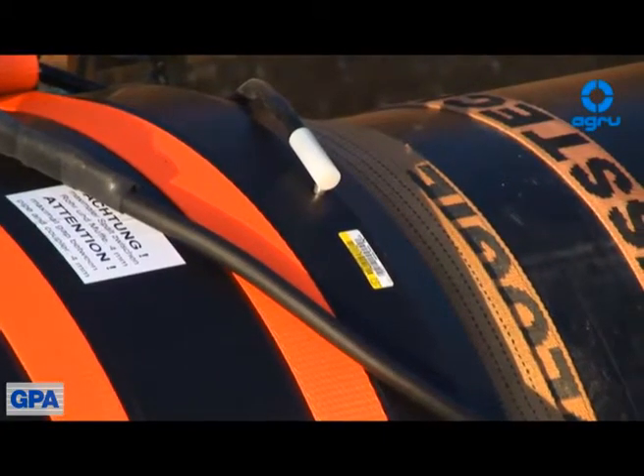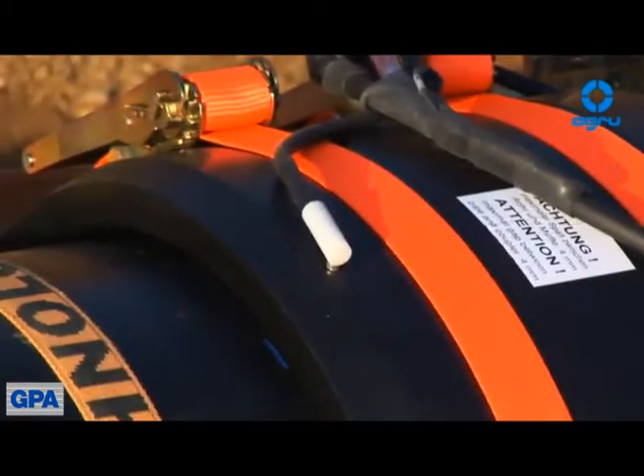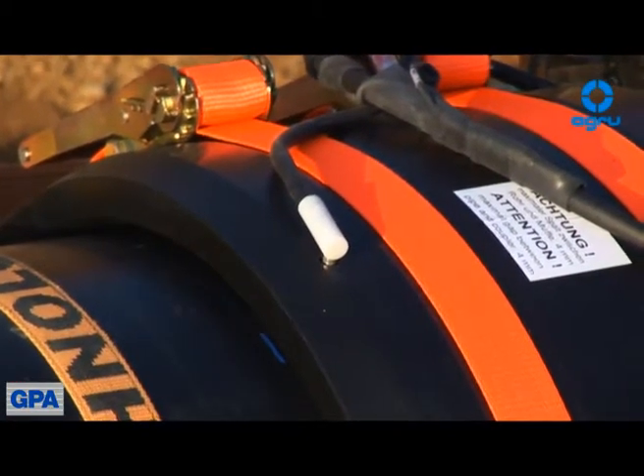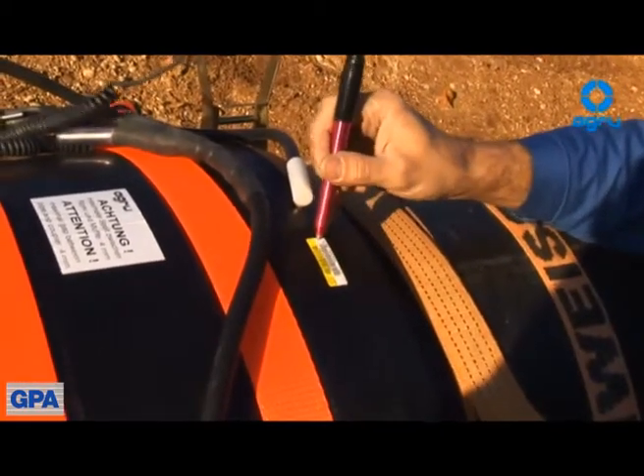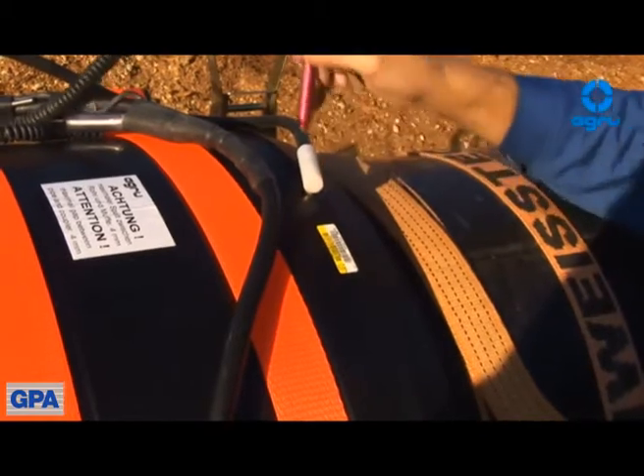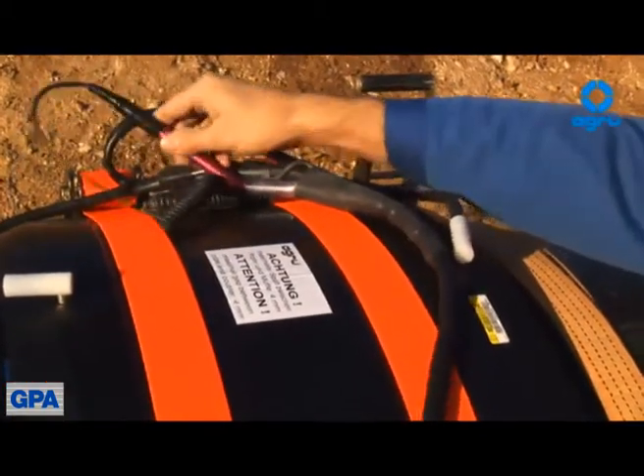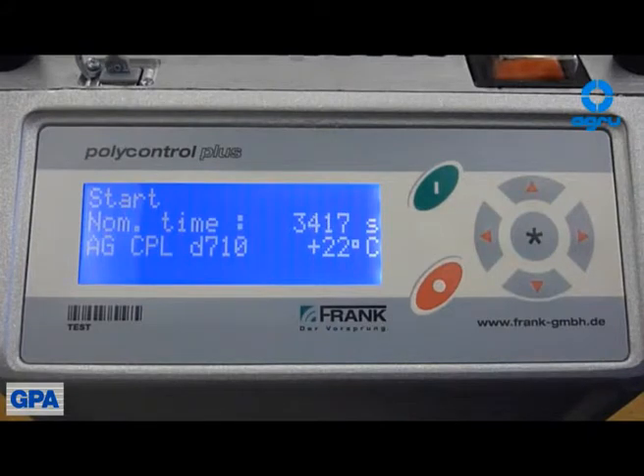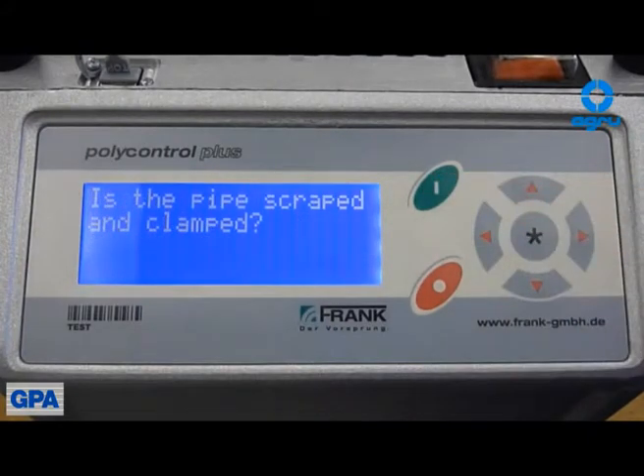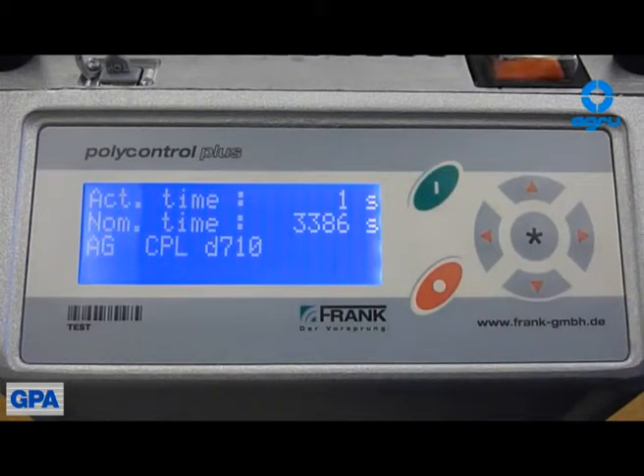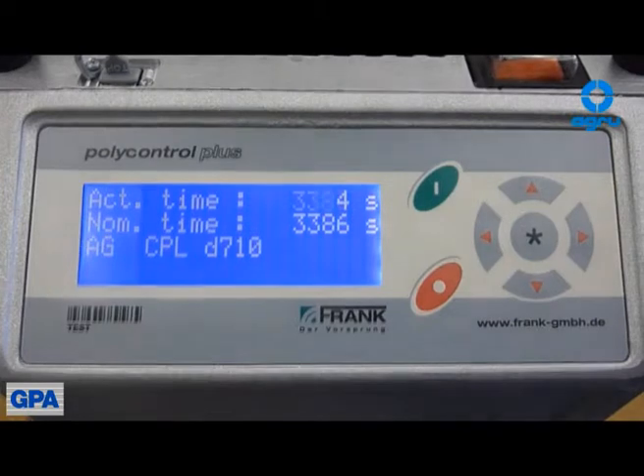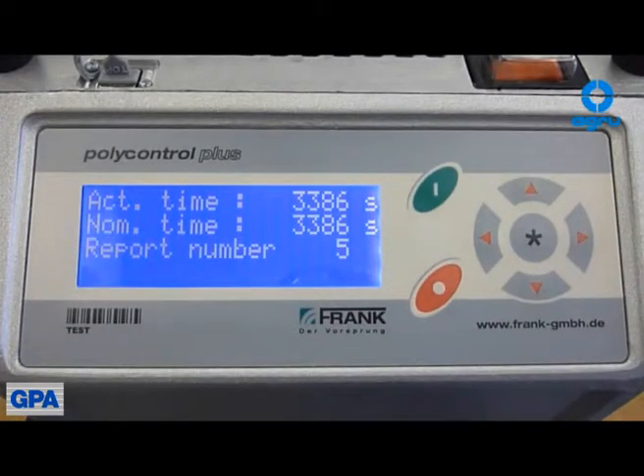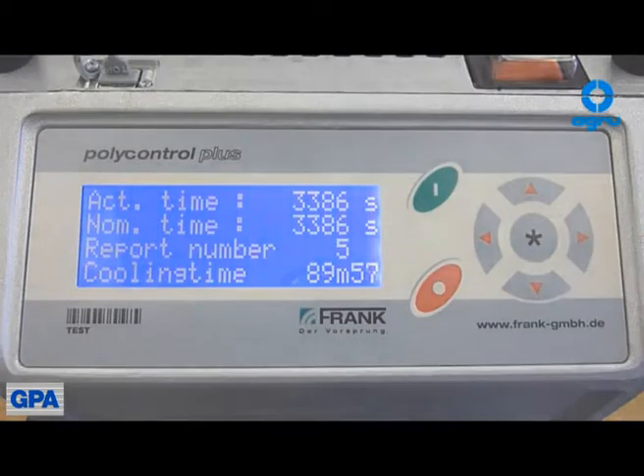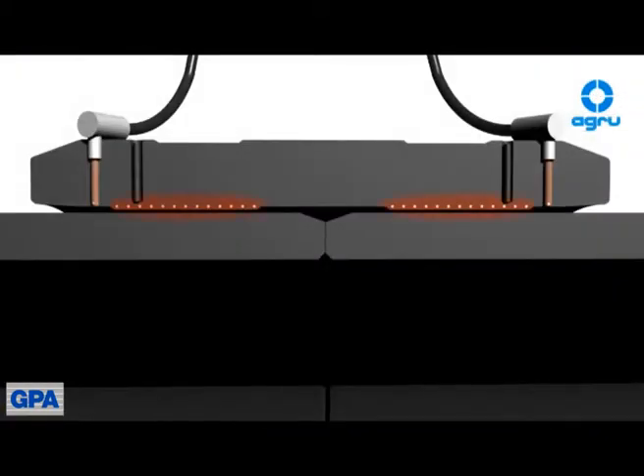For monofill E-couplers from OD 560mm up to OD 710mm, the required data for the welding process can be taken automatically from the welding equipment by scanning the specific component barcode. The data shown on the display have to comply with the component data. After starting the welding process, it runs automatically until the welding time is up. The annular gap between the E-coupler and the pipe will be closed during the plastification by the thermal expansion. Gaps from 2.9 up to 3.5 mm can be closed depending on the E-coupler dimension.